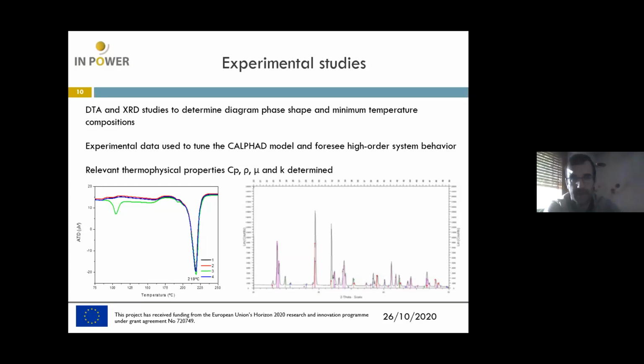Mainly differential thermal analysis and X-ray diffraction studies were used to determine the phase diagram shape and the minimum temperature compositions. The endothermic peaks of the DTA give you the information of what is the liquidus or the solidus of a given composition, and on the other hand, the XRD graphs can also give you the phases present in the solid state. So in terms of modelization, this can be used to tune the model developed in CALPHAD, to give a more robust model, and to give good results in the final case.